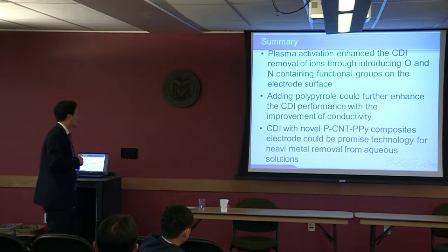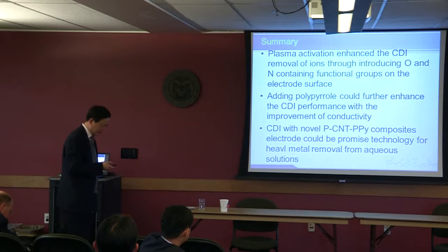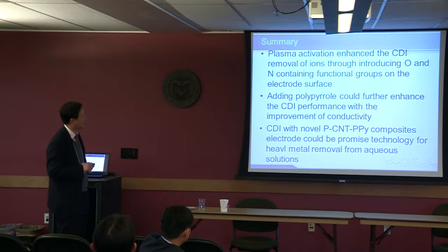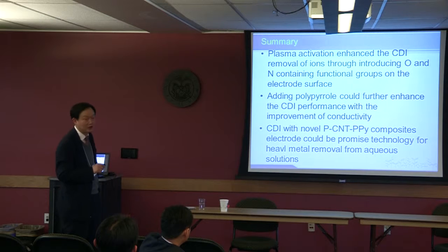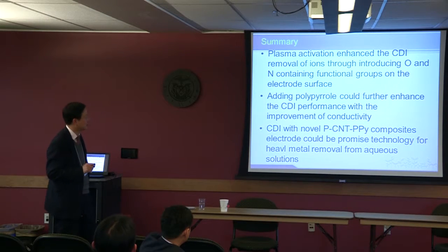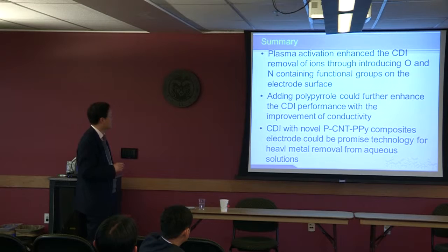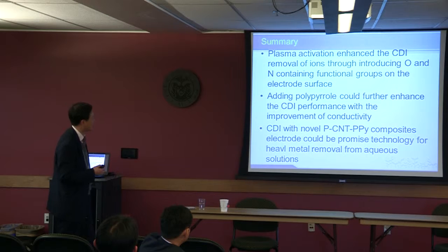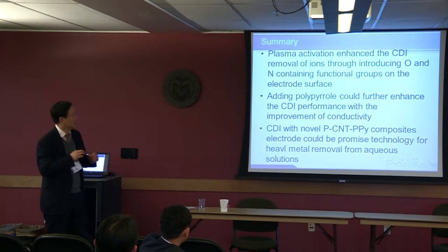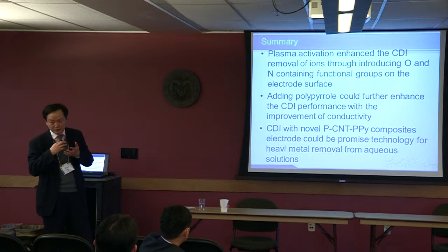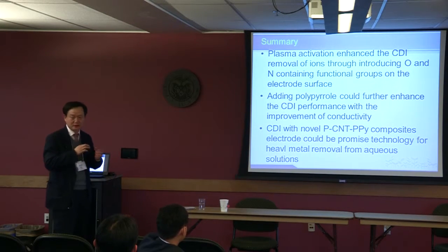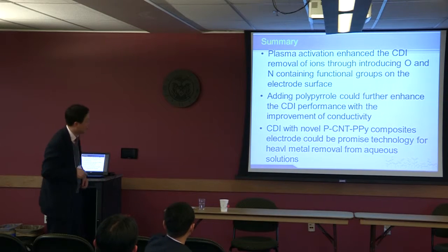Well, from the experiment, we can make some summaries. The first point is that plasma activation can enhance CDI removal of ions by introducing oxygen and nitrogen containing functional groups on the electrode surface. I think this kind of group can make the surface very polar and hydrophilic, so it can easily interact with the ions.